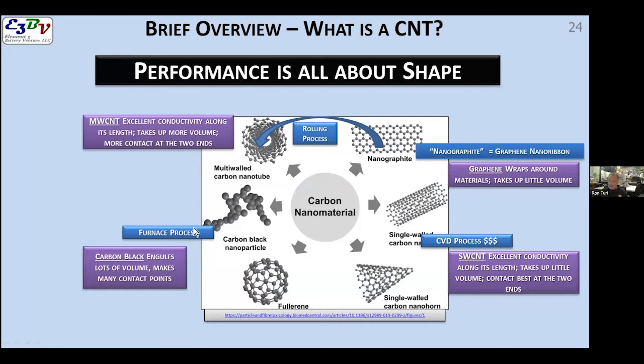If we look at carbon nanotubes, these are additives that most people think are in for improving the electronic conductivity, and they do, but that's often not the main reason that they go in. The main reason is to improve the integrity of the electrode as it cycles, especially for silicon. As it expands and contracts, the particles lose contact with each other. These things help you maintain contact with each other. So they help hold everything together to various degrees.